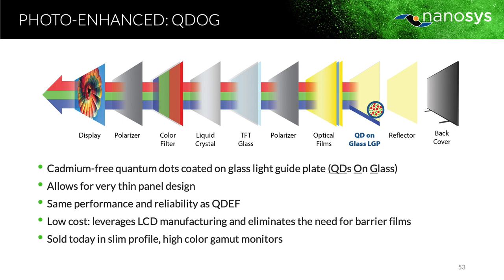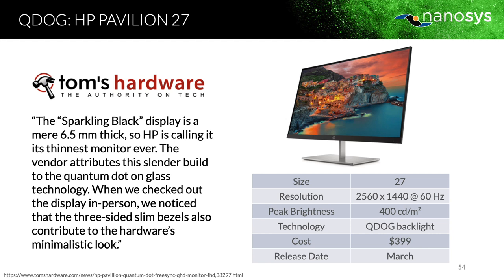In addition to quantum dot enhancement film, there's an analogous display architecture we call QDOG, or quantum dot on glass. Basically, it's very similar to the QDEF. It's the same idea, other than there's not a standalone film. Instead, the quantum dots are deposited directly on a glass light guide plate and integrated into the display that way. It has a very thin layer, about 10 microns thick, and there's no additional conversion film needed. And so it has all the properties of quantum dot enhancement film, but it does allow for a narrower display architecture. In fact, HP has a product now based on this technology. It's a monitor. It's only 6.5 millimeters thick. It's thinner than a smartphone. So there are some different ways that you can integrate quantum dots and displays that have different advantages.